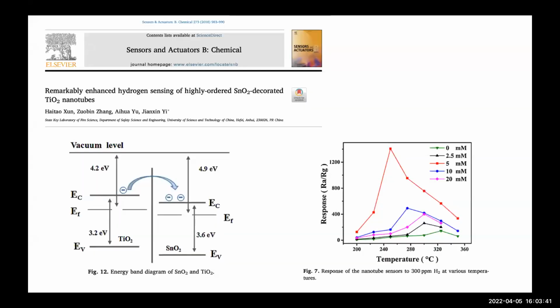Now next we will discuss the second paper, which is remarkably enhanced hydrogen sensing of highly ordered SnO2 decorated TiO2 nanotubes. In this paper you can see that TiO2 has a smaller work function than SnO2. Transfer of electrons from TiO2 to SnO2 would occur, leading to the formation of an electron depletion layer at the surface of TiO2, but an electron accumulation layer at the SnO2 surface, which increases resistance. This we will also discuss in the mechanism. So you can see the diagram of what actually happens in the mechanism.